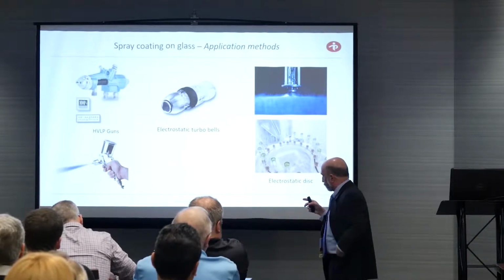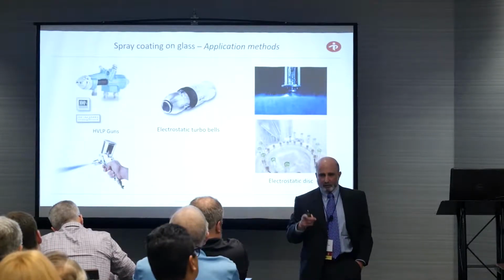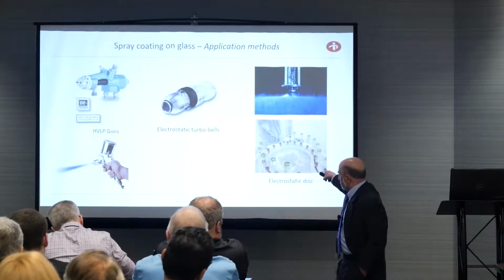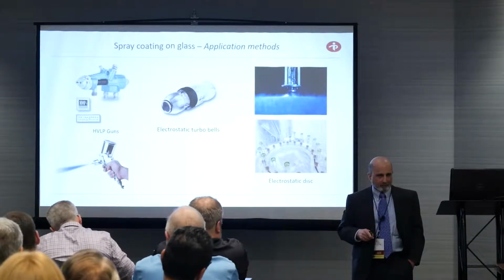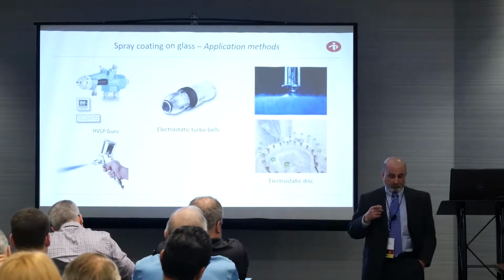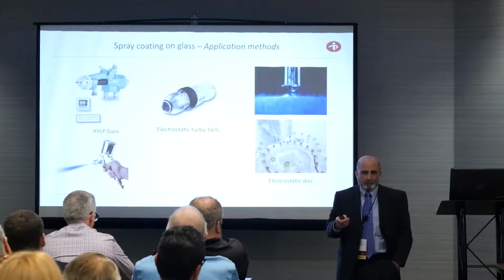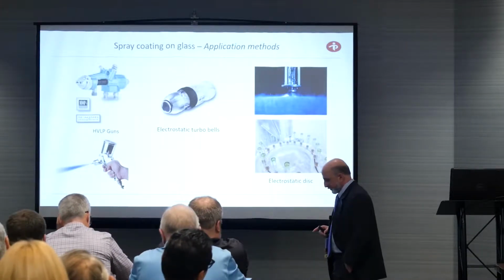These types of applicators all require coating manufacturers to design the coating for the proper applicator. Let me tell you what. Picture a disc moving at 24,000 RPMs. You're talking about a waterborne coating. If that system isn't designed to have the open time, by the time the droplets hit the object, it's going to be dry, right? Sure, physics, right? So we have to formulate our coatings to be able to do that.